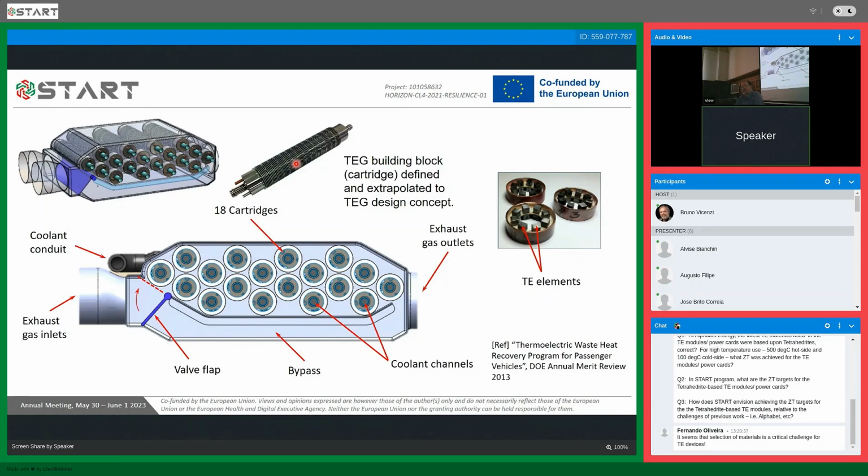So not just the hero material that you make in the lab, but as we were trying to scale that up, being able to consistently have the same level of ZT was certainly another one of those challenges. I want to say it was in the 0.7 to 0.8 range in the scaled up fashion. But again, that was still at that development phase of things.